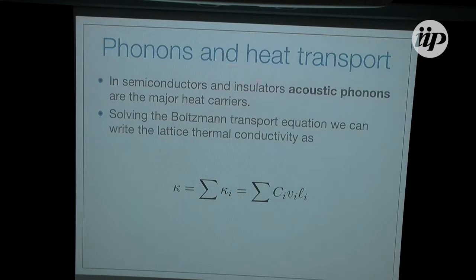So in a semiconductor or insulator, the acoustic phonons are the major heat carriers. And then you can solve the Boltzmann transport equation, as mentioned this morning. Under the simplest approximation you can make, in the end, you can write the thermal conductivity of a material as the sum of the thermal conductivity of each phonon mode, which is given by this product of the heat capacity, the phonon group velocities, and the mean free path. Now, the specific heat for each mode is easy to write. The phonon group velocities are just the derivatives of the frequency with respect to the wave vector. So once you have the phonon dispersion, you can easily calculate this as well.